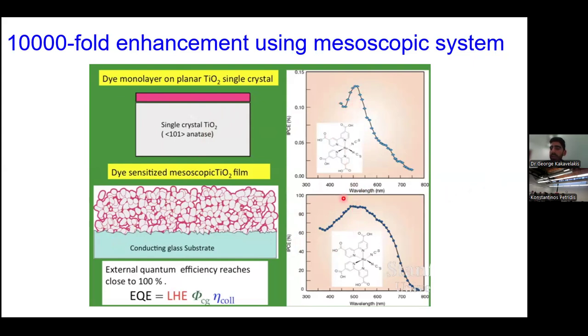And this was amazing because you imagine the thickness of the dye here is self-assembled at 2 to 3 nanometers. So with a 2 nanometer thick semiconductor, you can have 90% quantum efficiency, and for silicon to do so, you need 100 to 300 micrometers. Can you imagine how groundbreaking this behavior was? And this was nominated several times for the Nobel Prize. The Nobel Prize was given to lithium-ion batteries a few years ago, and that's why I believe they will never give it to the dye-sensitized solar cell, because the operation is very similar.